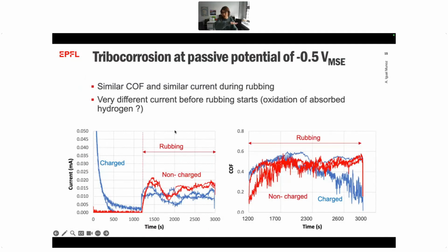Then we go to the other situation. Now we apply a passive film. So we form in a well-controlled way a surface film on top of it. And here the protocol is always the same. We impose the electrochemical conditions and we register the current. So we already see from the non-charged red curve with respect to the blue a difference from the beginning. The non-charged sample shows a very low current at the beginning. Of course, at the onset of rubbing, the current increases because we are mechanically detaching this oxide layer and accelerating the corrosion of the underlying metal. So current increases. In the charged sample, in this case, when imposing the electrochemical conditions, we have an abrupt, huge increase in current, and then an exponential recovery. So this is typically we are oxidizing something. What we are oxidizing, we will see in a moment.